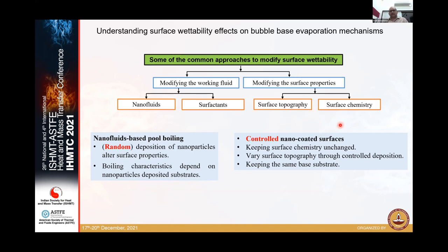But in whatever literature is currently available, we have not yet encountered many studies which have decoupled the effects of these two methodologies. Mainly people have used methods which lead to the modification of the surface topography as well as surface chemistry. So it becomes hard to comment on how one of these two factors is going to affect the bubble-based evaporation mechanism. When it comes to nanofluids, the central idea is that if you conduct a boiling experiment with nanofluids, with evaporation, you will have the sedimentation or deposition of the nanoparticles on the substrate surface, which would lead to a change in the wettability.